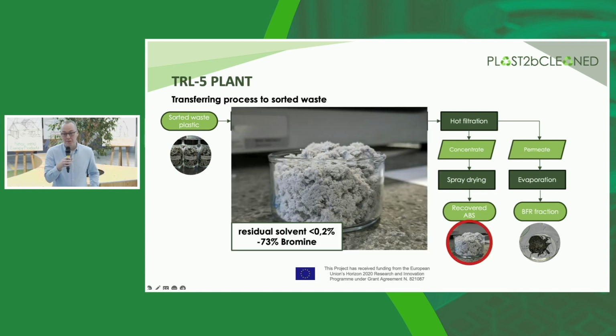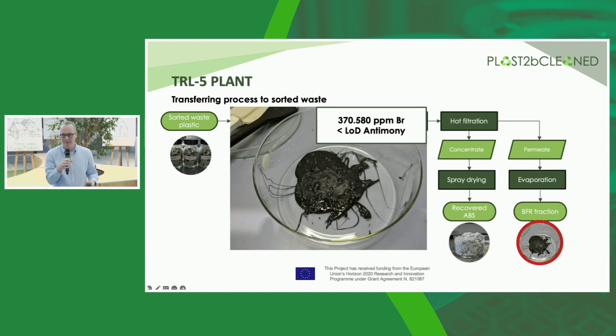But when we look at the recovered ABS, we still have quite good results. We reach a residual solvent content below 0.2%, and unfortunately not the 95% bromine reduction, but a 73% bromine reduction in this case. Still a good target and a good starting point for further development. Also, the bromine fraction we recovered, you saw the picture before, was a nice yellowish granular powder. Obviously, when we turn to real waste, even though it's sorted, you see that there are a lot more additives that make this fraction a bit tricky. But this is something that our partners at ICL are looking into, how to process that into bromine that can be used.